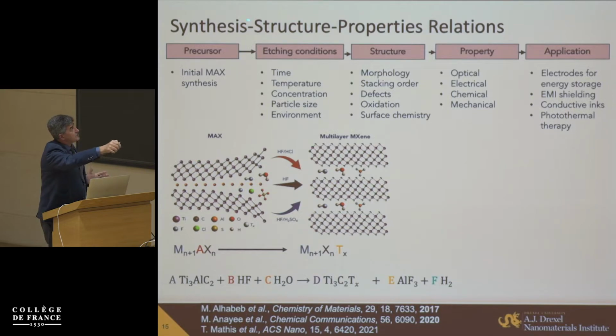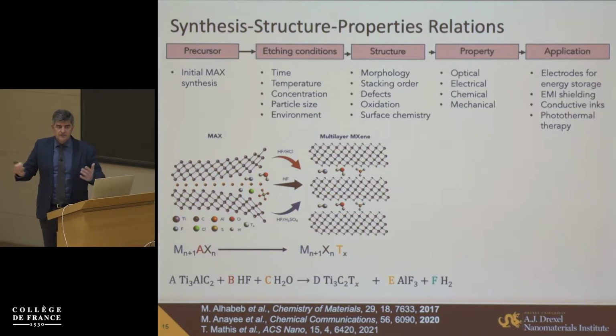You start from synthesis, actually from the precursor. MAX phases, stoichiometry, and grain size already contribute here. Synthesis, these etching conditions, lead to controlled morphology, structure, surface chemistry, defects, stacking, and so on. And those control the properties of the materials. If we know properties, then we can move to application. Based on properties, we can design applications. But again, using current computational facilities, you can actually start with the application and the properties you need and go back to the composition and structure that may provide these properties. We're not completely there with predictive modeling, but it's moving in this direction. And in some cases, we can control that this is happening.